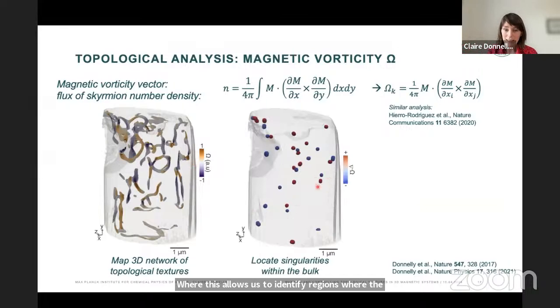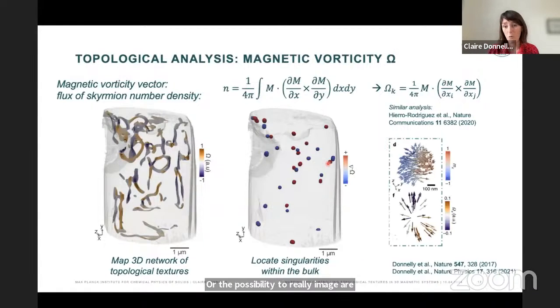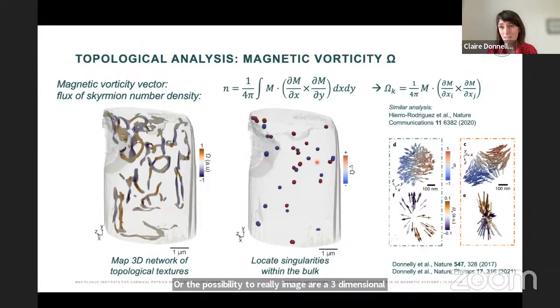But we can also go one step further, and we can look at the divergence of this vorticity vector, where this allows us to identify regions where the topology changes abruptly. And when we do this, we suddenly have the possibility to really image our three-dimensional distribution of these Bloch point singularities, where these red and blue points essentially correspond to Bloch points and anti-Bloch points within our system. Now with this first access to this three-dimensional distribution of Bloch points, it really opens up the possibility to not only track them efficiently within these 3D data sets, but also to look into how they may interact with each other across these three-dimensional spaces.